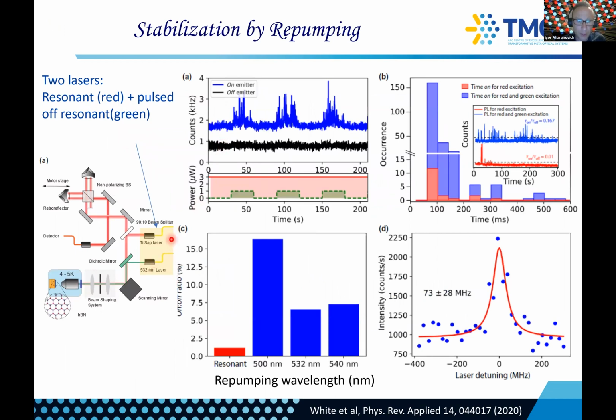And so what repumping does is, in addition to your resonant laser, which is illustrated here, you put a second laser off resonance, so with the green laser here. And the mechanism of why this works is actually still under debate. Most likely, under resonant excitation, you're kicking out the charge state from the defect. And so if your defect has been, for example, in a 0 charge state, by ionizing it, it becomes plus or doubly or negative. And what the green laser does is basically reinitialize the system.